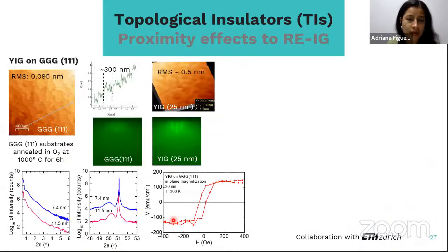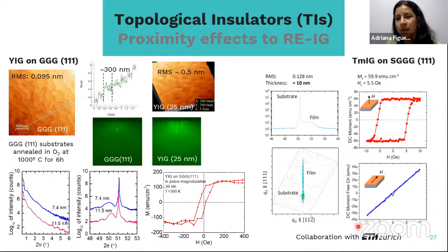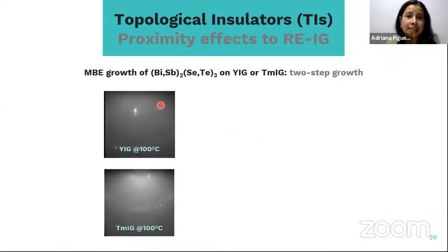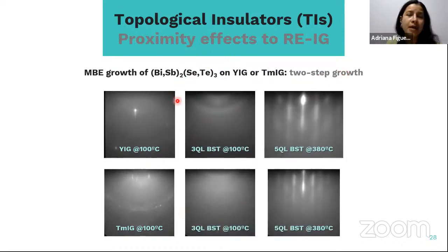So just to show you that we also have epitaxial growth of these materials. Here I'm just showing the results of the growth for YIG, the yttrium iron garnet, on the substrates. We perform some pre-treatment of the substrates in order to have very good quality of the garnets. And for the thulium iron garnet, we collaborate with people at ETH Zurich who provide these films. So we have these two kinds of systems, and then we grow the TIs on top. In this case, for the growth of the topological insulators on our MBE machine, we perform a two-step growth, which means that we grow first a buffer layer, or a seed layer, at low temperatures, and then we anneal to the growth temperatures, and then we continue with the growth, and we end up with very nice layers at the end of the growth.